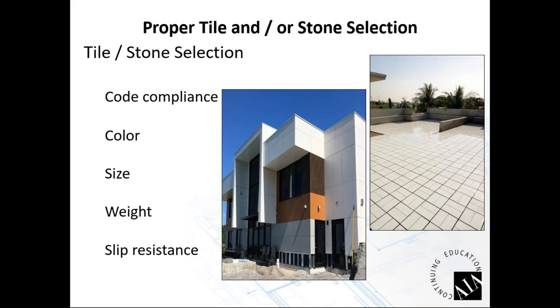So the use of a dark tile in that condition is probably not the smartest thing that could have been done. We talked about the size of the tile and the limitations, not only the facial dimensions, but the overall weight, if we're going to be doing a direct bond or mechanical anchoring, being aware of the weight. And then if we're putting an exterior tile for a wear surface, a walking surface, making sure that we're complying with slip resistance with that tile so we don't have a slip and fall situation.